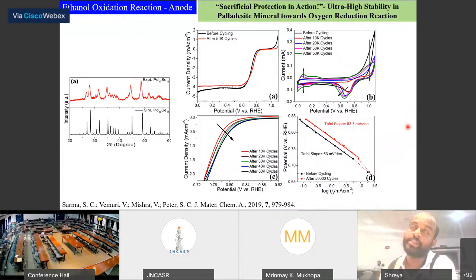So we synthesized this material in the lab, characterized it by various methods, and then did the oxygen reduction test, and ethanol oxidation also. But what we are pointing out here is the oxygen reduction reaction. Here you can see that when a cycling process happens, up to 50K cycles, there is no change, which is a kind of record data.